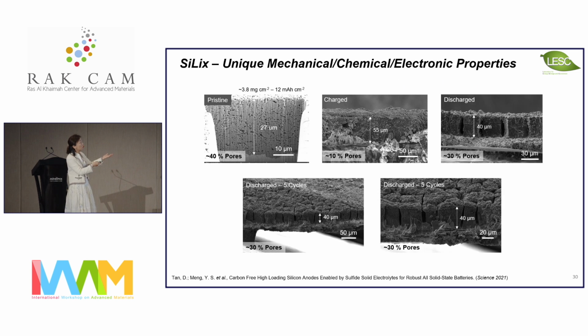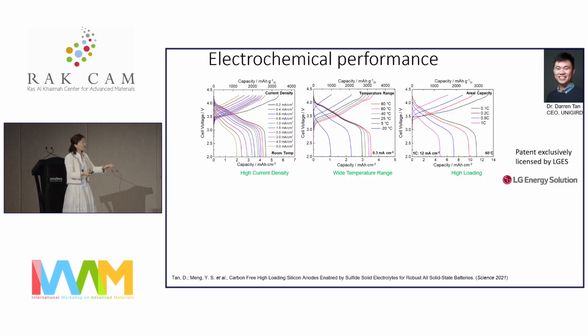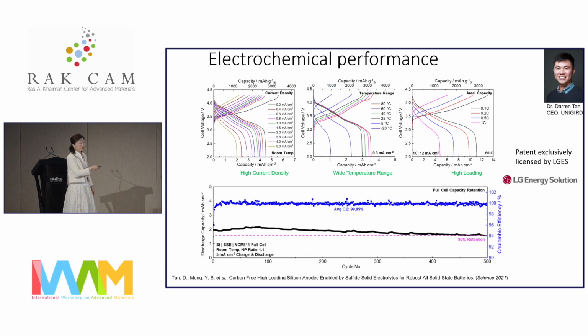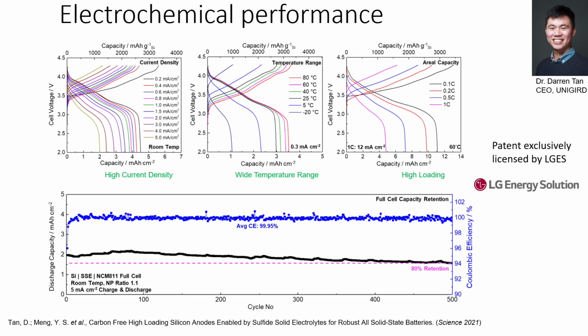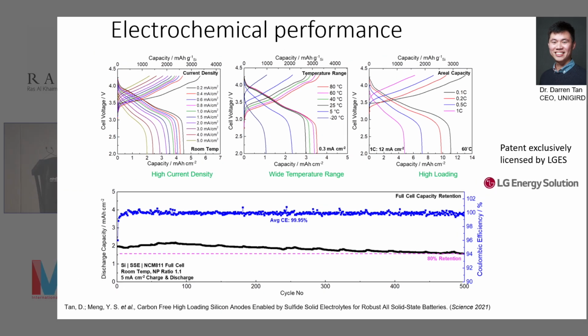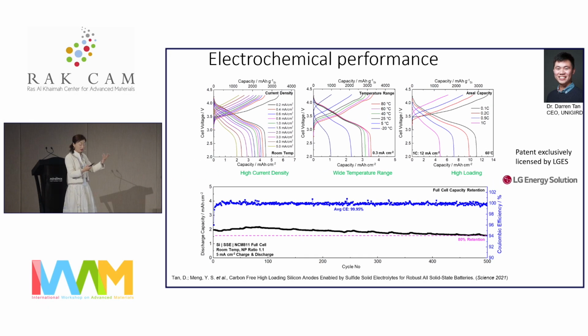We have more evidence to show you. After the first cycle, the silicon anode dimension is stable. And because of this discovery, we were able to make an average Coulombic efficiency of 99.95, and the cell can cycle for very, very long cycles. And this resulted in a patent that is exclusively licensed by LG Energy Solution, who is looking into the solid-state battery commercialization possibility. It's not fully confirmed yet, but they decided to take this patent just in case. Yeah, so my PhD student, Darren Tan, actually worked on sodium, but for his PhD, he did some really good work for lithium solid state.